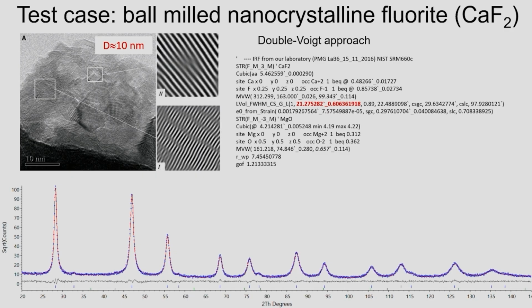If you want to play with this, fluorite, CaF2. And the reason is because it has a very low shear modulus. So the material is very easy to shear, and so it's full of dislocations if you manage to introduce them. If you crystallize it, probably you don't find any. But if you ball mill it, for example, it makes a hell of a number of dislocations.